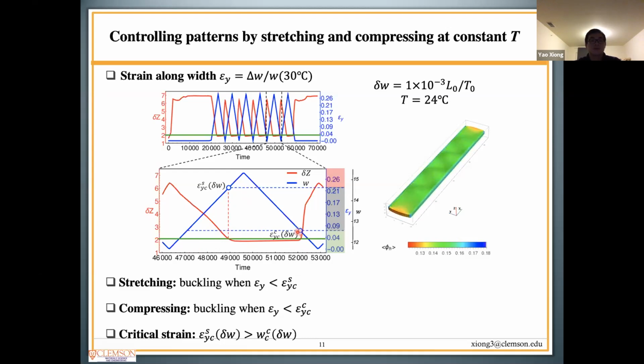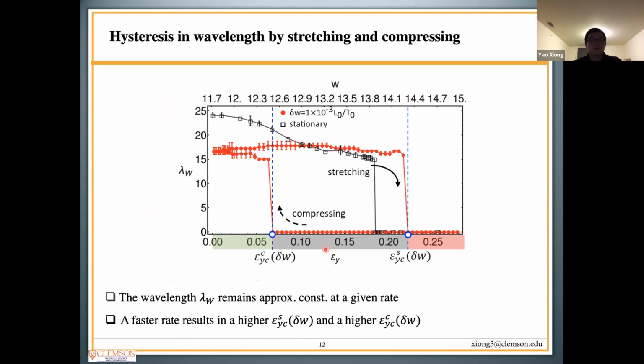As a result, the strain can be separated into 3 regions. In the red region, no buckling is observed during either stretching or compressing. In the gray region, only the stretched sample shows buckling, and in the green region, we observe buckling during both processes. By using stretching-compressing cycles, we also observe the hysteresis loop in the wavelengths. Compared with the stationary case where patterns are fully developed in gels with constant width, we found the wavelength of the dynamically controlled sample can remain approximately constant. A faster rate shifts both critical strains during stretching and compressing to higher values.